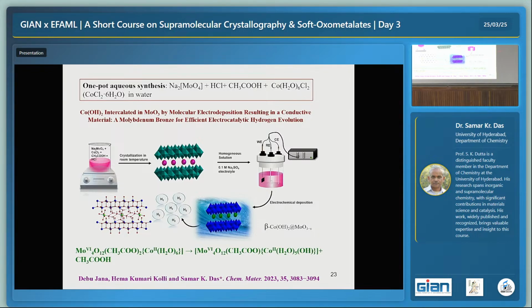You may ask me, maybe if it is the beta form, it will come out as a physical mixture, the beta hydroxide and MoO3 side by side. It is intercalated. We checked by PXRD because the 2 theta angle will shift to the lower side if it is intercalated. So that way we proved that even in acidic medium you can generate intercalated beta cobalt hydroxide. It is also a molybdenum bronze now because some of the Mo is in the reduced state, and it has a very shiny lustrous color. If you run continuous hydrogen evolution day and day, week and week, nothing happens once it is deposited on the electrode.